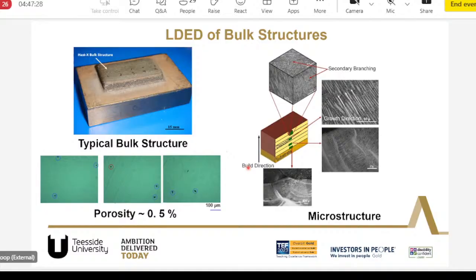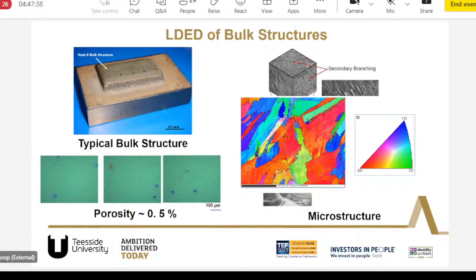So then we went down to the microstructure analysis. As you can see, non-homogeneous microstructure is there. We can see a lot of cellular dendritic growth, and as opposed to conventional manufacturing, we can see a lot of preferred growth along the 100 plane.